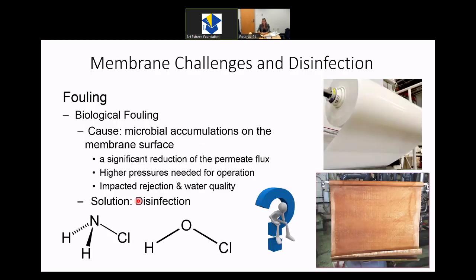So remember when I said one of the challenges that membranes face is fouling. There are many types of fouling, but one of the main ones that I will focus on is called biofouling. Biofouling is a microbial accumulation on the membrane surface, and when this happens, there's a significant reduction in permeate flux. You need higher operating pressure for these membranes to clean water. Again, these are high pressure membranes, so when there's a coating on them, you need more pressure to push the water through. And you have impacted rejection and water quality. So on the right side there, you see what a clean membrane looks like. This is not the spiral wound element, but this is what would be spiral wound inside. And then you have the biofouled membrane underneath.